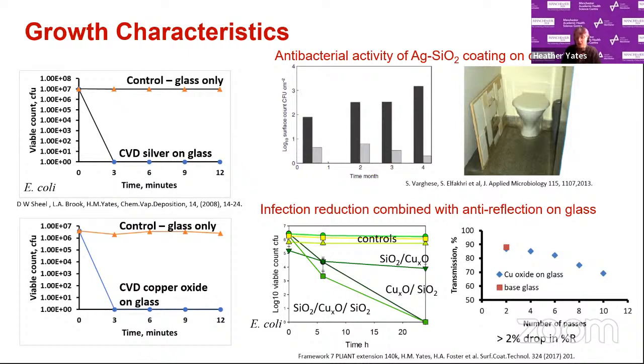On the bottom, I was looking at touch screens that get a lot of use, and to have an anti-reflection layer on them, which is what the silica makes, to make them clearer. But if you could add an antibacterial property to it at the same time, it would reduce the transmission of infection. So we did a mixture of silica, copper oxide.